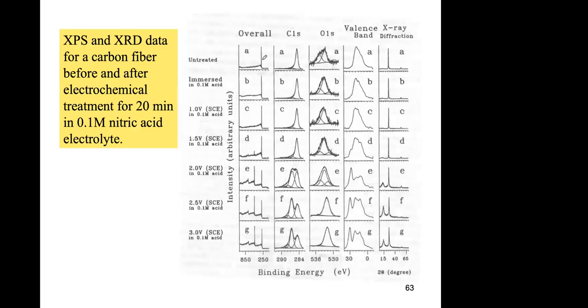So this is an example of a carbon electrode. It's a carbon fiber before and after electrochemical treatment. So basically they are trying to oxidize the carbon. So you can see here that this is one volt applied in an electrochemical cell in acid, up to 3 volts. So in this direction, you're increasing the oxidation of the carbon. If you increase the oxidation of the carbon, you will have more carbon functionalities on the electrode.